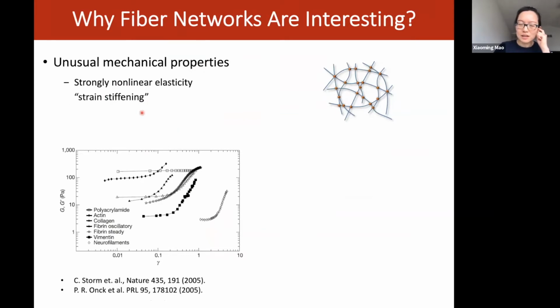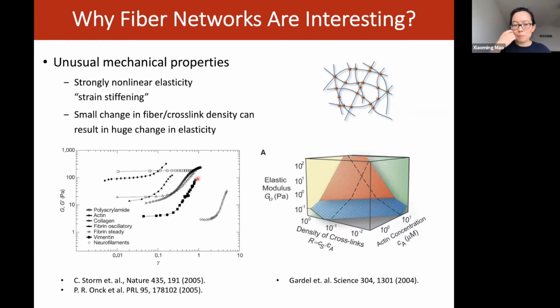So for example, many of us know about this phenomenon of strain stiffening in fiber network materials, where as you give the network a nonlinear strain, the elastic moduli can jump by more than an order of magnitude. So this is one interesting nonlinear elasticity behavior. And even if you stay in linear elasticity, the elasticity can be very sensitive to geometric parameters in the network, such as the density of crosslinks and the density of the fibers. And as you change these parameters, the elastic moduli can also jump by orders of magnitude. So this sensitive change of elasticity as you change some geometric parameters indicates that there may be some kind of underlying mechanical critical point that gives you this sensitive response.